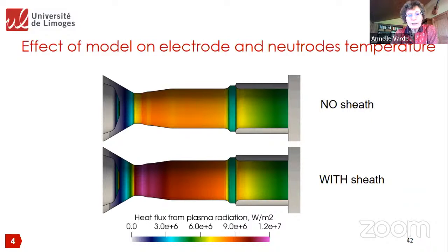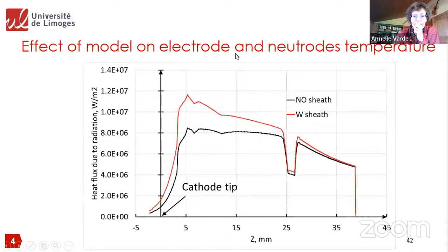But now, if we look at the temperature of the electrode and of the neutrode, you can see that because we have this higher current density on the cathode tip, we will have a higher heat flux to the electrode and the neutrode. As you can see here, and you can see here the variation of the heat flux due to radiation along the neutrode stack. And you can see that it changes. This is the anode ring. Here is the neutrode stack. Here is the cathode tip. And you can see that you have a rather strong increase when you add the cathode sheath.